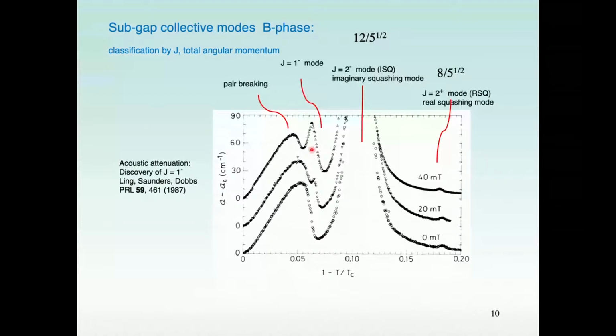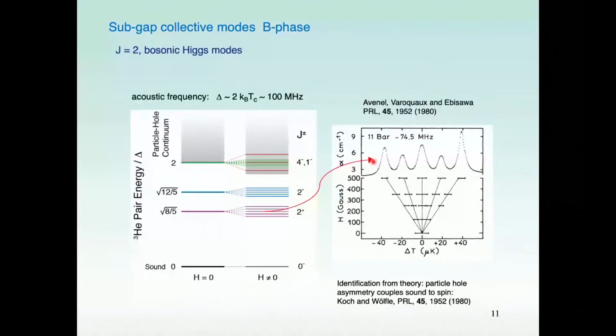Now, if indeed this J=2 set of states, which can be thought of as bosonic Higgs modes, with a total angular momentum of 2, you might anticipate in the presence of a magnetic field that you'll see a splitting. And indeed, shortly after the discovery of this 8/5 mode, Avenel, Varoquaux and Ebisawa in Paris showed this beautiful 5-fold splitting of the attenuation peaks in the superfluid helium-3 B phase.